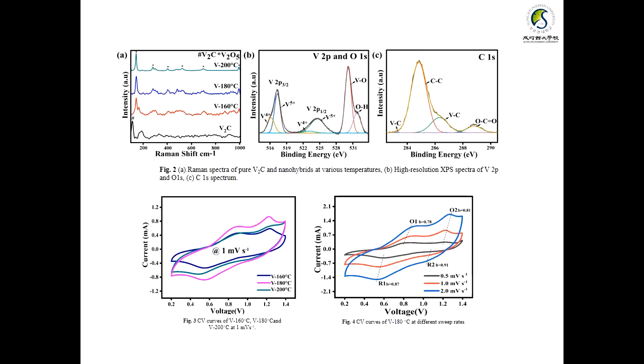a multi-oxidation state was present, with V4+ and V3+ and V5+ states present, and the C1s also denotes that the oxygen content and carbon content are bonded to each other. Coming to the CV characterization, in the CV curve at a fixed scan rate of 1 millivolt per second, I could see that the 180 degrees centigrade sample shows better capacitance when compared to the 160 and 200.